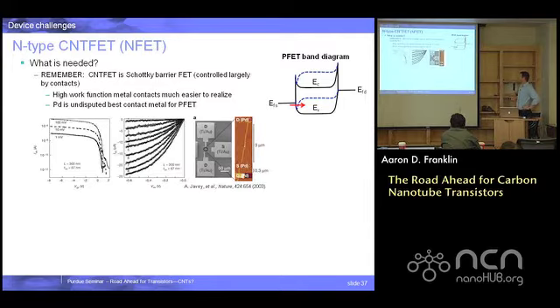It's a lot easier to make a PFET from carbon nanotubes. It is a mistake that people say carbon nanotubes are naturally p-type, because they are not. They are intrinsic semiconductors. They have no natural doping or charge present. You have to put that into the nanotube, and so the way you put it in determines the polarity. And getting a high work function metal like palladium or gold is a lot more straightforward than a low work function metal like erbium that oxidizes very readily. So that's why most of them, almost all of them, have been PFETs.